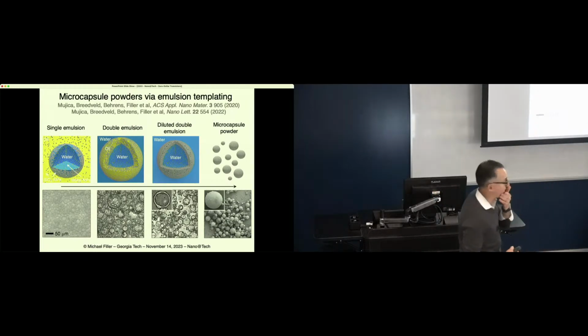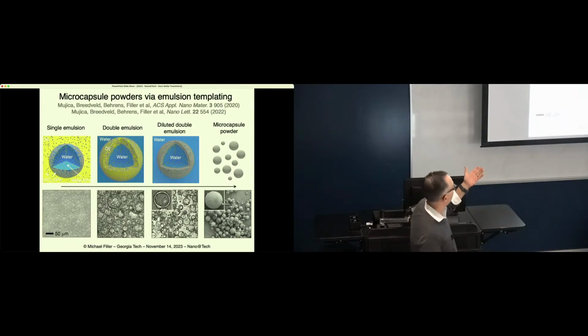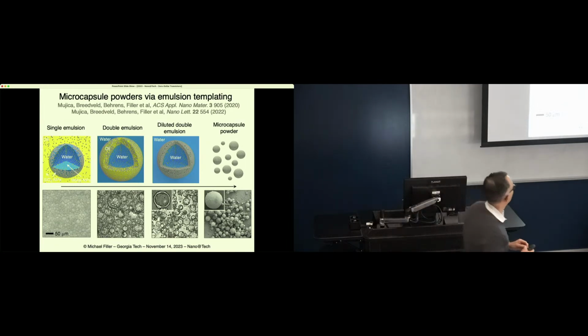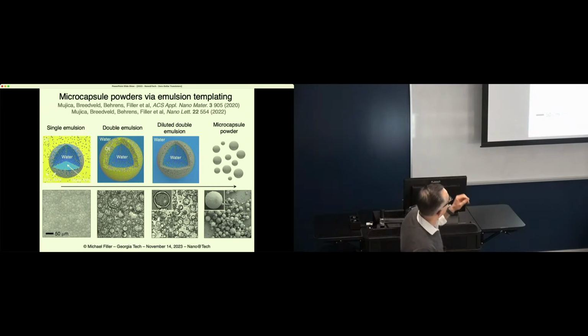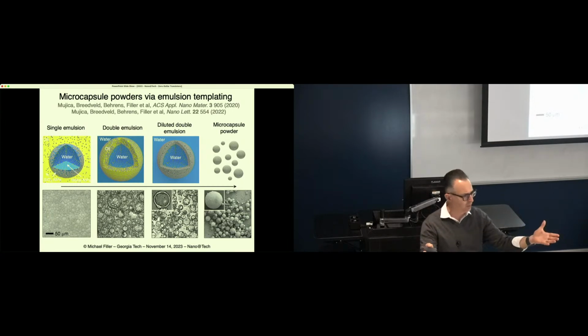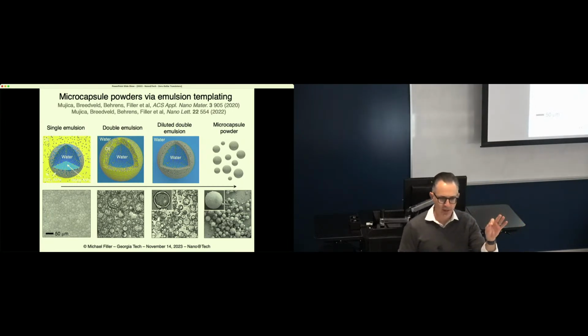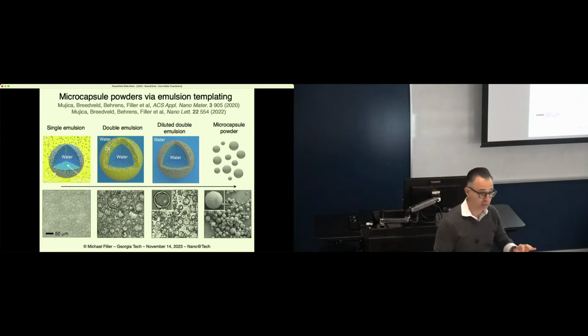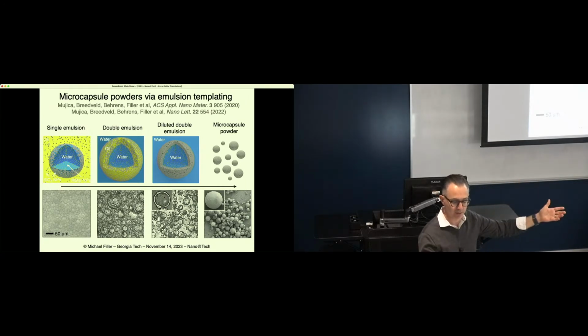Okay, so how do we make the capsules? We have to start there. That is an emulsion templating process, which I collaborate very closely with my colleagues Victor Breedveld and Sven Behrens. We start with a single emulsion, which are these water droplets in a continuous oil phase. And the metal particles are decorated with a molecule that makes them hydrophilic, so they're happy to go into those water droplets. The silica that's going to form the shell is slightly hydrophobic. It's happy to go into the oil phase.